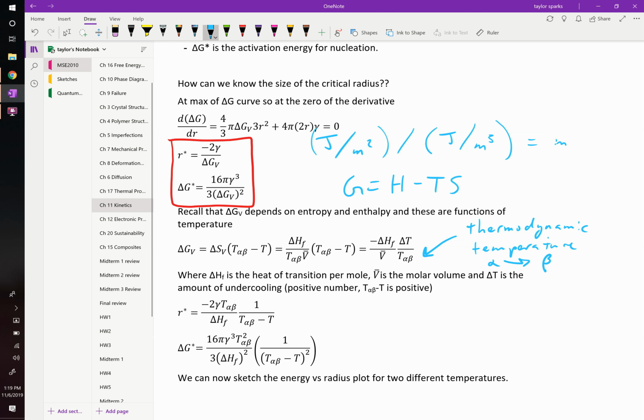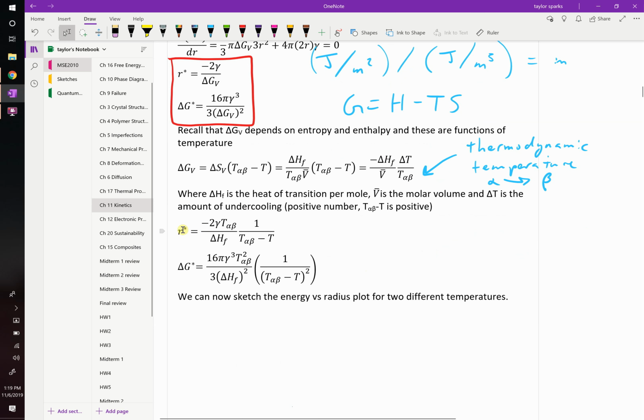Everybody with me? Delta HF is going to be your change in enthalpy of formation. When you go from that phase to another phase, you're forming a new phase, so you could look up the enthalpy. We did this in chapter 16. We used changes in enthalpy already, so you've seen that. There's the change in temperature, delta T. V is the molar volume. So in other words, you could look all those things up, and you could figure out what delta GV is. Once you do that, they substitute this value in for your r star and delta G star equations. And you get, finally, these.